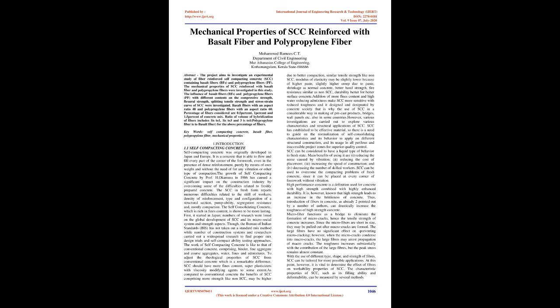The influence of basalt fibers, BFs, and polypropylene fibers, PF, with different contents on the compressive strength, flexural strength, splitting tensile strength and stress-strain curve of SCC were investigated. Basalt fibers with an aspect ratio 48 and polypropylene fibers with an aspect ratio 60. Percentage of fibers considered are 0.5%, 1%, and 1.5% of concrete mix.